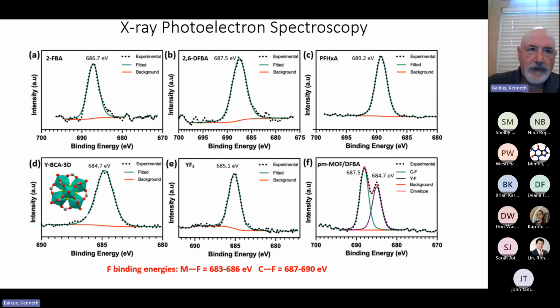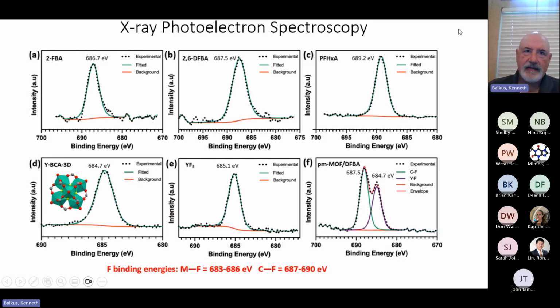If you look at just the fluorine in these structures, and I should point out, if you look at the starting material, this is 2-fluorobenzoic acid. It has a binding energy at 686.7. This is the 2,6-difluorobenzoic acid. And then, jumping ahead a little bit, here's the perfluorohexanoic acid, PFAS, and that's at 689. So what you see is all these organofluorine compounds are roughly in the same place, between 687 and 689 electron volts.